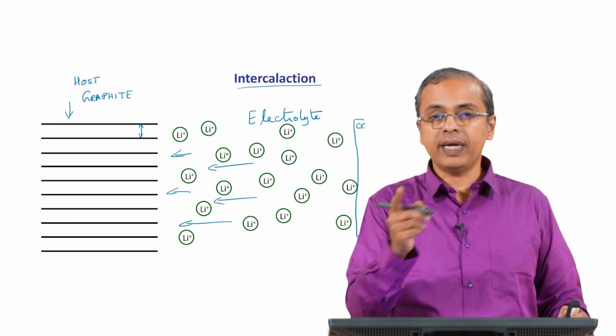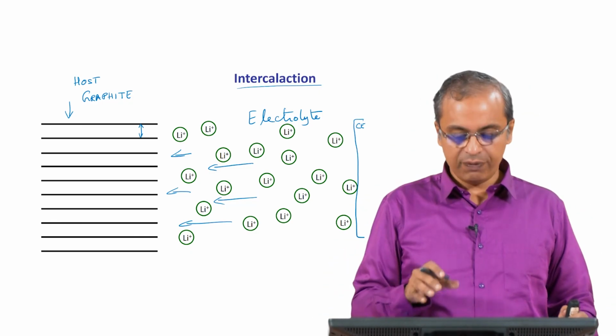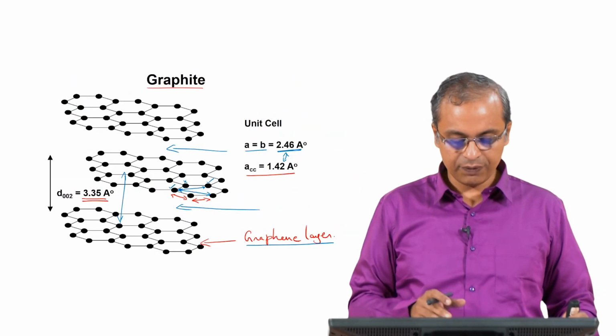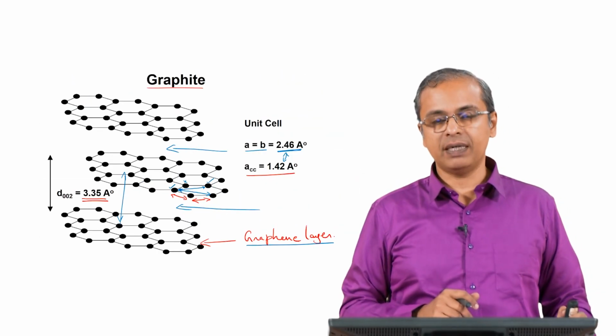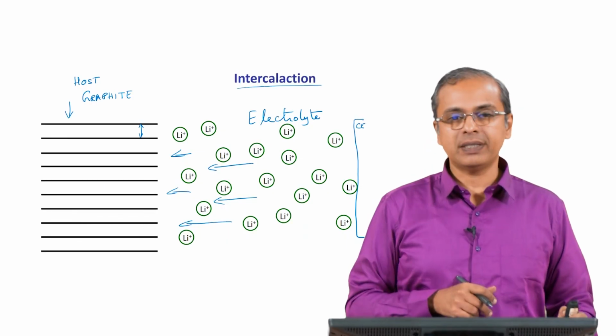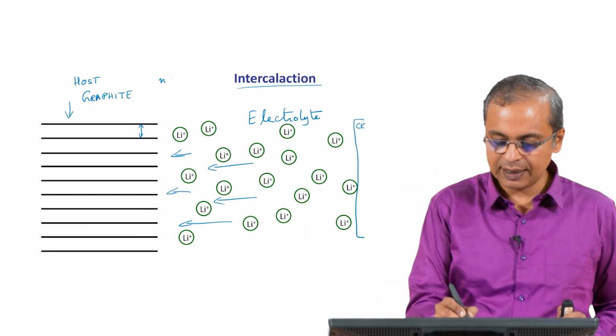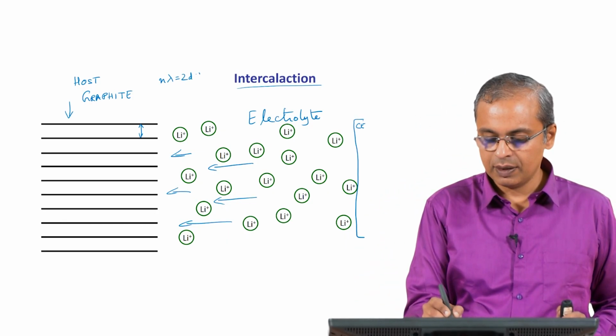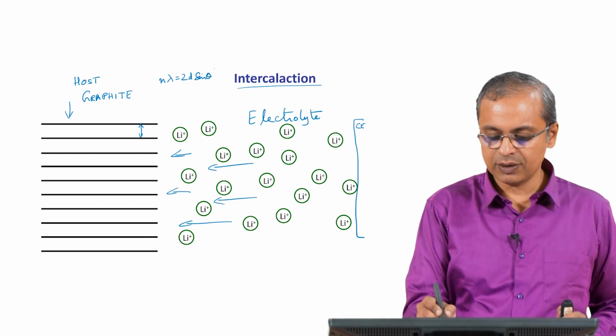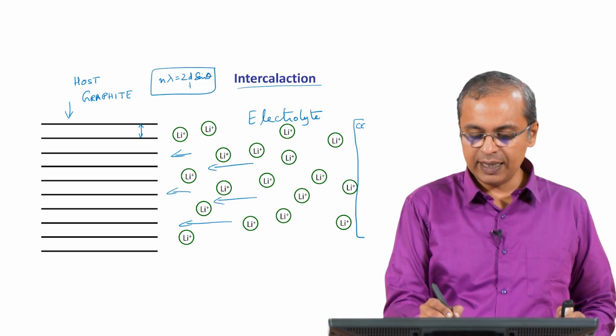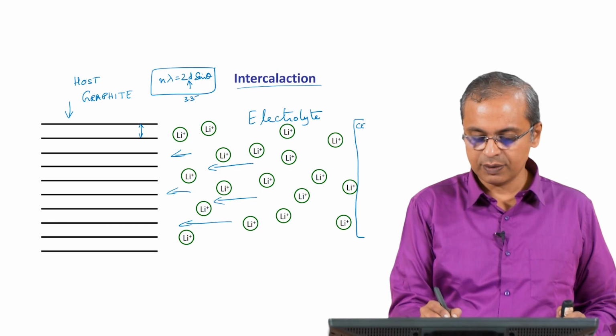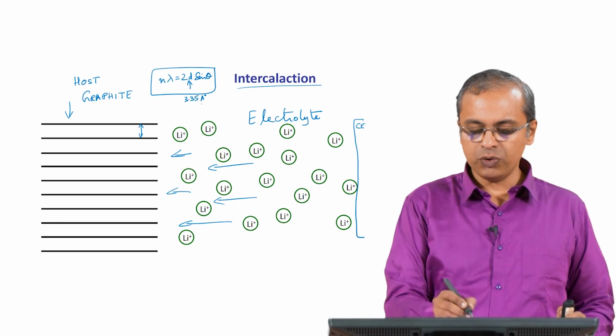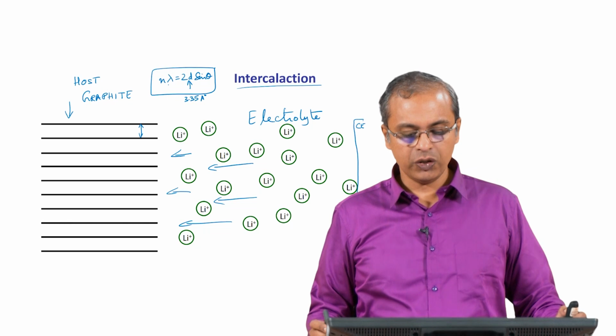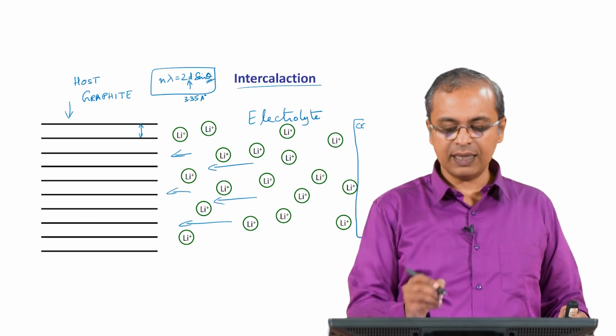So, when you do X-ray diffraction of the cell, you will find that this initial spacing that we had, this 002 spacing of 3.35 angstroms. When you do X-ray diffraction, if you do n lambda equals 2d sin theta, which is the Bragg equation, right, this d is 3.35 angstroms.